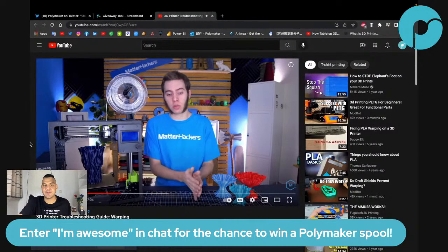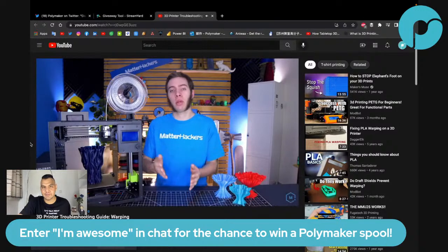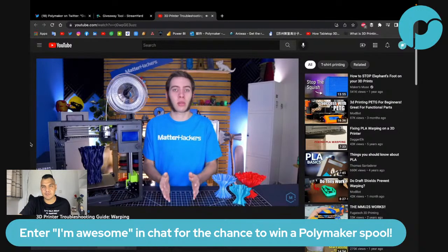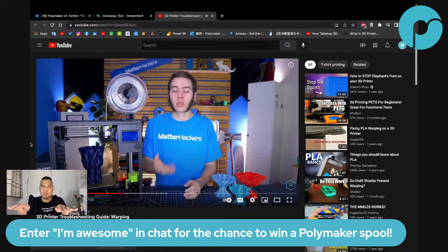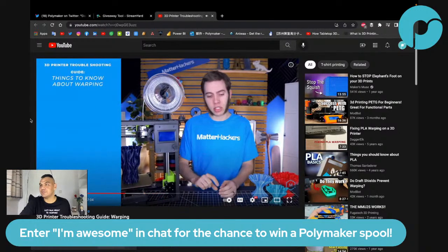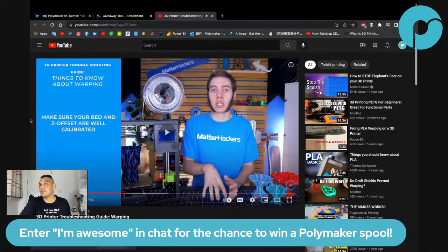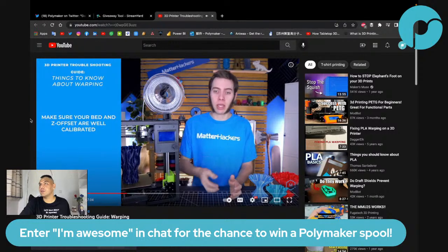Squeezing out into itself. So it's pushing the previous pass up, which just reduces the layer adhesion in the beginning. And it's not pushing up, right? It's pushing sideways, but the accumulation is going to go up, right? Well, which is the same. Maybe I'm a little bit picky here. But it's not warping. I don't want people to think, oh, I'm printing too close, my part is warping. No. There's a sweet spot where your Z offset's at just the right height, where your part's sticking well enough, but it's not picking up.